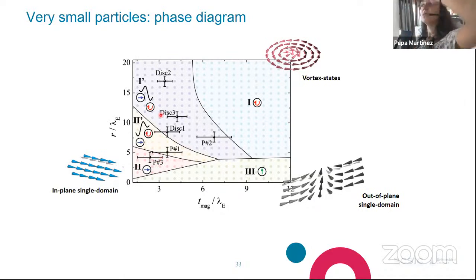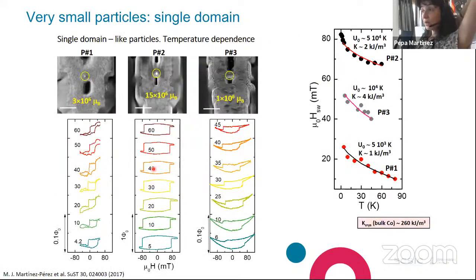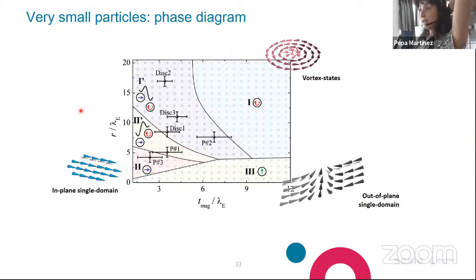To understand this, we fabricated a number of particles that you can see highlighted here. P1, P2, and P3 exhibited single domain behavior. This is proved by this quasi-square, or almost square, hysteresis loops measured with the nanoSQUIDs that you can see here. Let me highlight that these particles are now extremely small, having magnetic moments of just 10^6 Bohr magnetons.